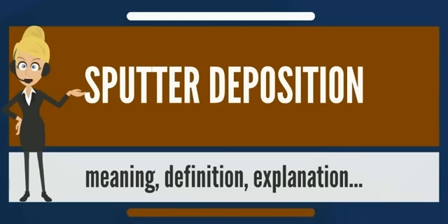The sputtered atoms are neutrally charged and so are unaffected by the magnetic trap. Charge buildup on insulating targets can be avoided with the use of RF sputtering where the sign of the anode-cathode bias is varied at a high rate, commonly 13.56 MHz. RF sputtering works well to produce highly insulating oxide films, but with the added expense of RF power supplies and impedance matching networks. Stray magnetic fields leaking from ferromagnetic targets also disturb the sputtering process. Specially designed sputter guns with unusually strong permanent magnets must often be used in compensation.